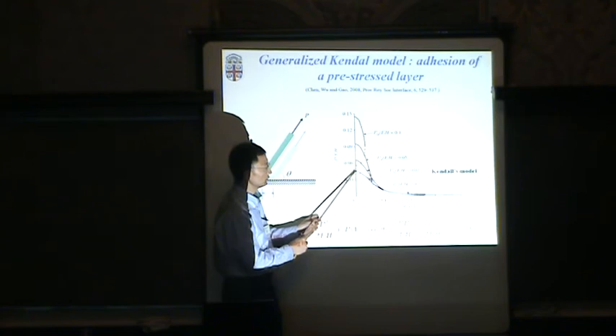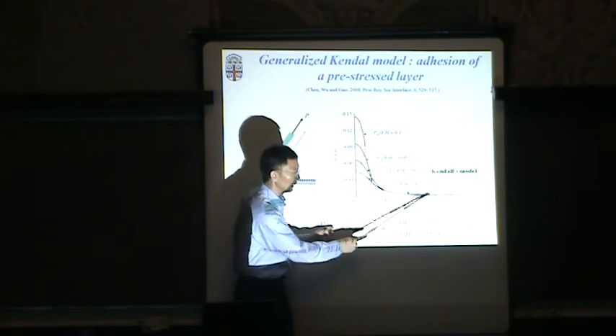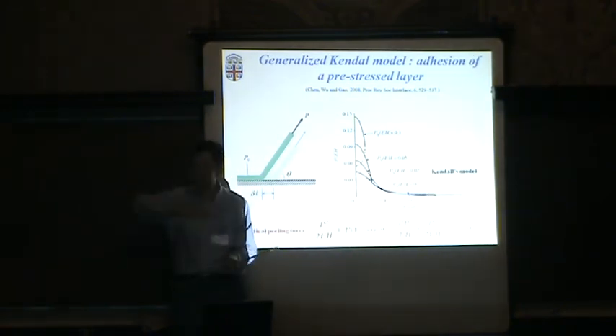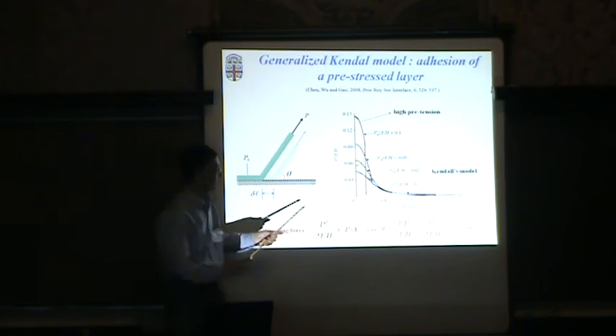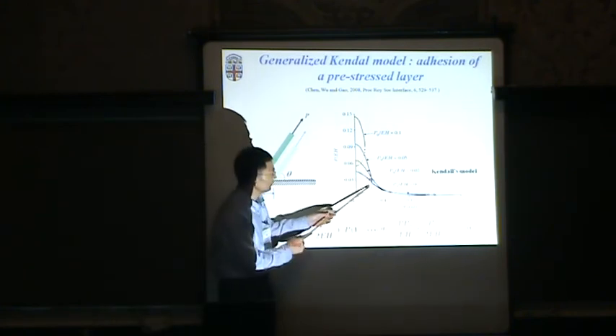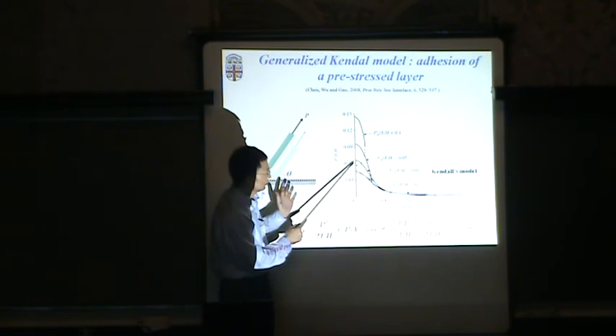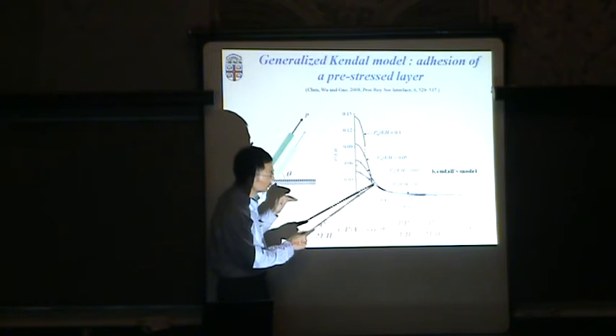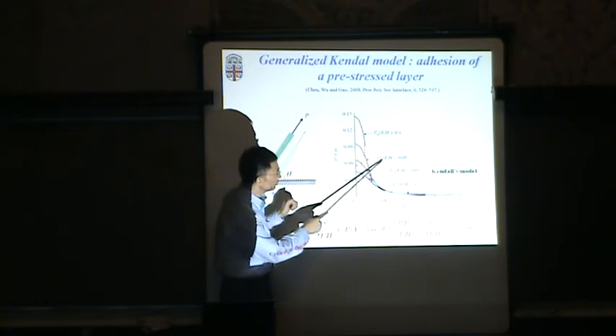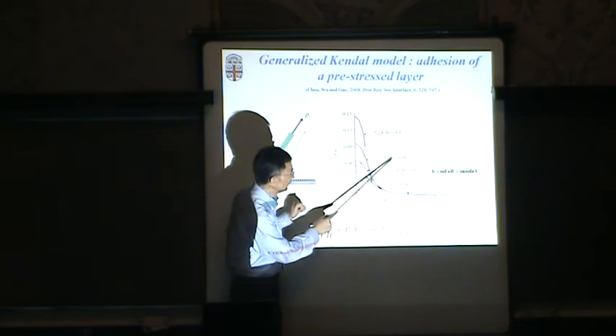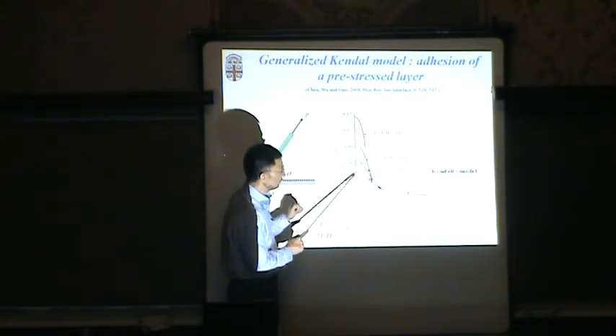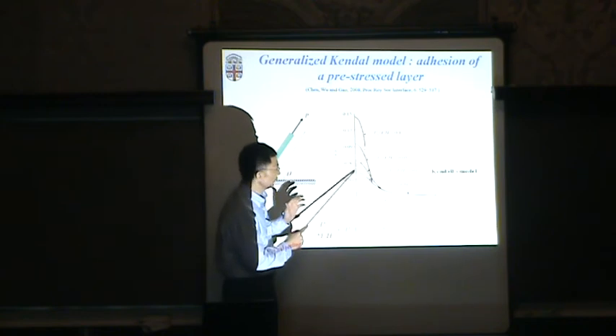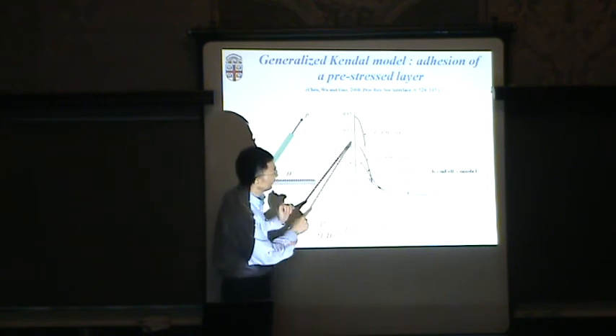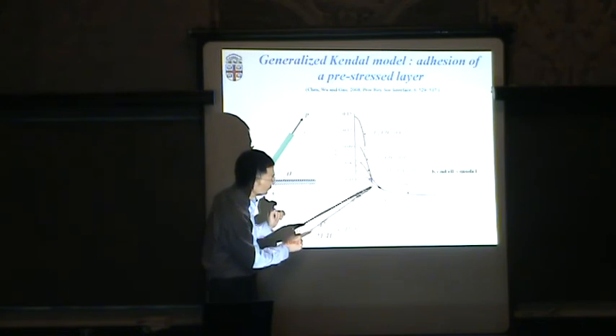Adhesion is maximum at 0 and then decreases smoothly toward larger angles. Now we're increasing pre-stress. What you observe is the adhesion force at low angle increases, but still smooth. But then at a critical pre-stress, P0 over EH equal to 0.05, there's a drastic qualitative change. Even though before it had smooth behavior, you now get a stable branch here and an unstable branch here.